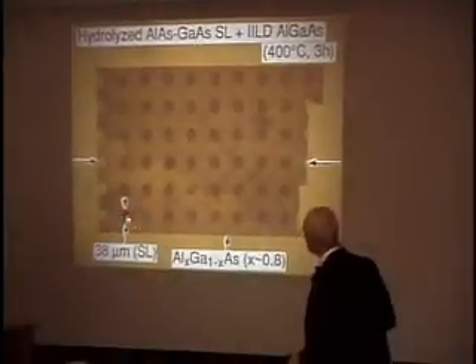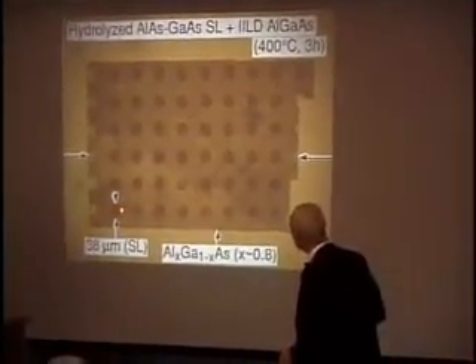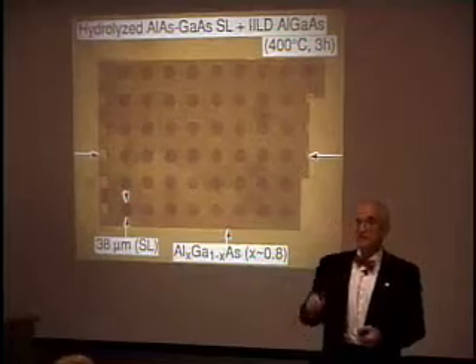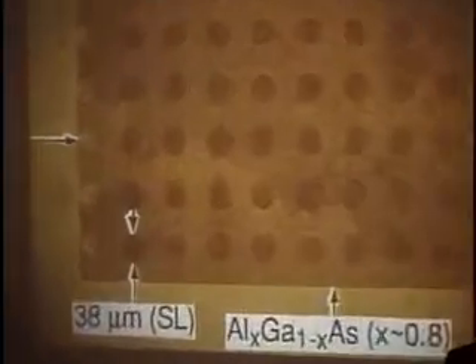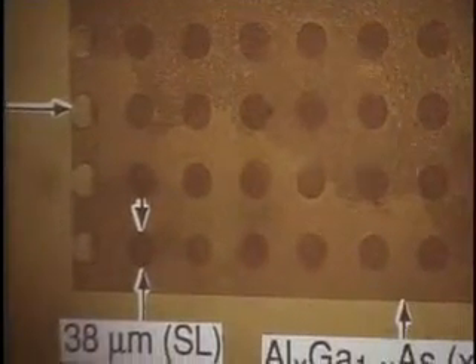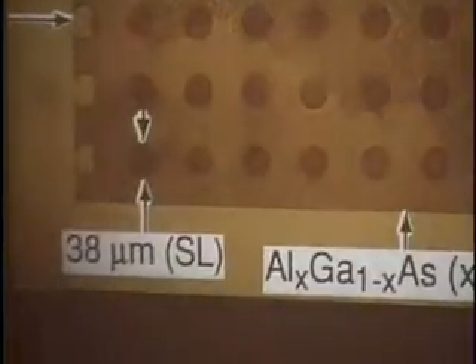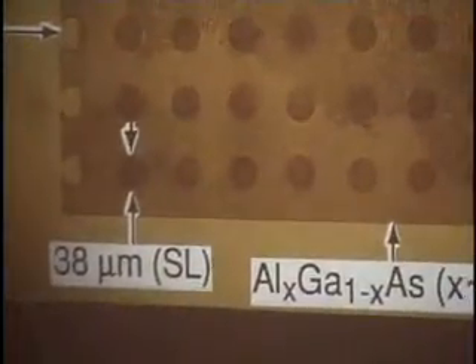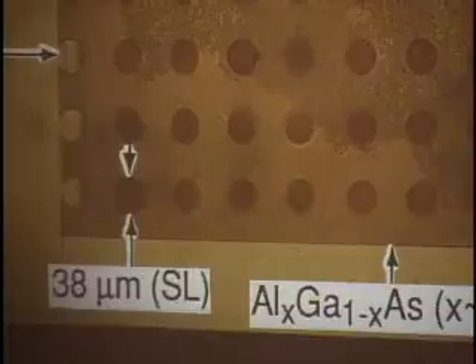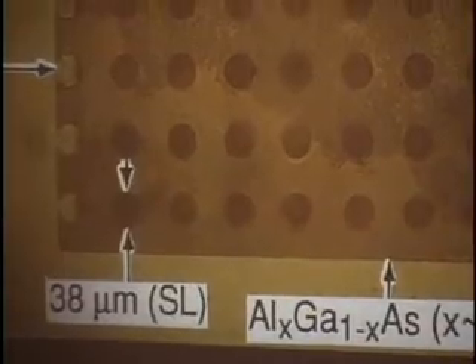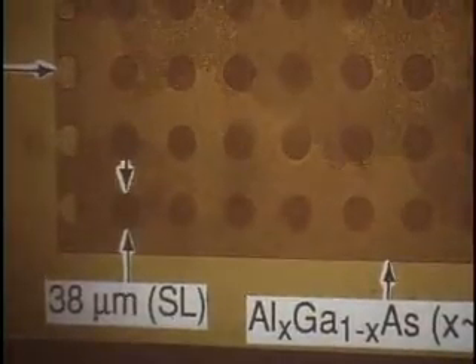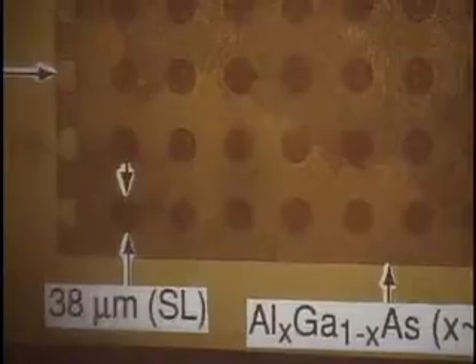Here is a stack. Focus on this region right here. This is a superlattice. This is gallium arsenide 45 angstroms, 150 angstroms aluminum arsenide, then a stack of material like that. If you take the substrate off, we didn't do a good job over here, but we did right here of taking the substrate off. We look through there with visible light. We see the nice red superlattice.